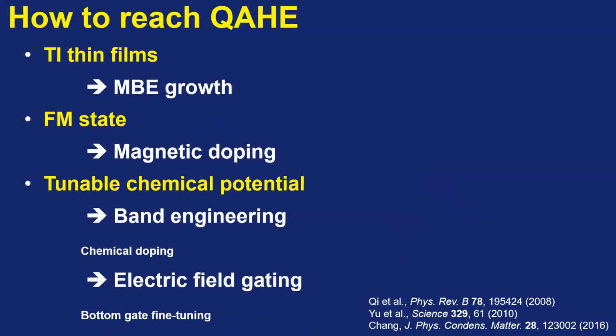In the experiment, if we want to realize the quantum anomalous Hall effect, there are 3 steps. The first step is we need a very thin film of topological insulator, so our approach is MBE growth. The second, we need to introduce ferromagnetic order into the topological insulator thin film to break the time reversal symmetry. Our approach is magnetic doping. The third step is we need to carefully tune the chemical potential into the magnetization gap. This is also the most challenging step. In our experiment, we take 2 ways: one is chemical doping, the other is the gating effect.